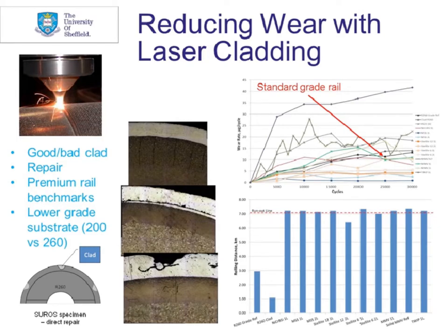I say that gives you a well bonded layer. You have to work hard to understand the cladding parameters you need to achieve that good bond and to make sure the heat affected zone isn't becoming embrittled with too much martensite. So it does take some time to get those parameters right.